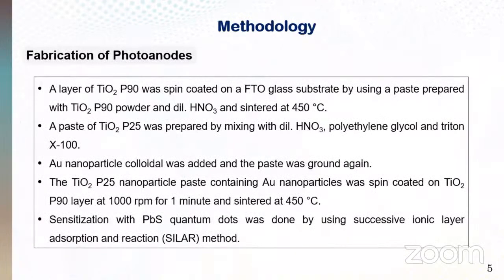When preparing photoanodes, a compact layer of TiO2 was first deposited on a pre-cleaned FTO glass substrate by spin coating a paste prepared with TiO2 P90. For that, 0.25 gram of TiO2 P90 powder was ground well with 1 milliliter of 0.1 M nitric acid. The paste was spin coated on the FTO glass at 3000 rpm for 1 minute and sintered at 450 degrees Celsius for 45 minutes. Then, a paste of TiO2 P25 was prepared by mixing 1 milliliter of dilute nitric acid, a drop of polyethylene glycol, a drop of Triton X-100 and 0.25 gram of TiO2 P25.